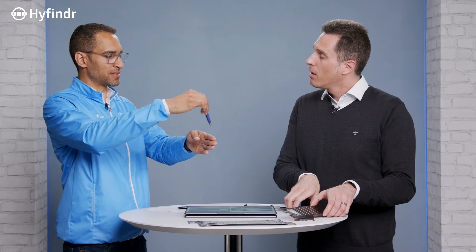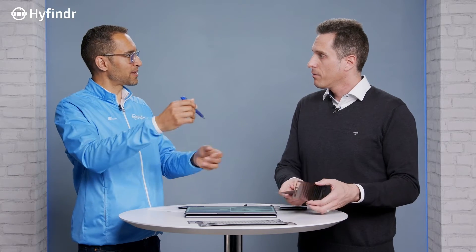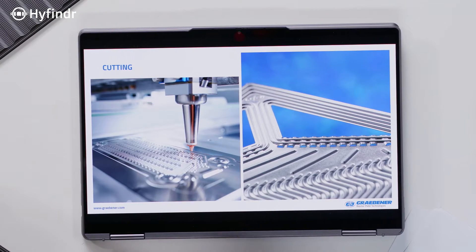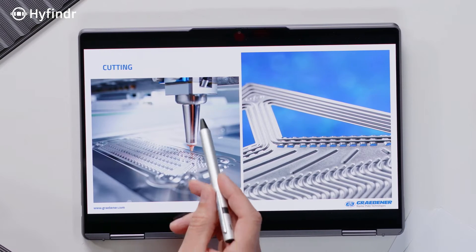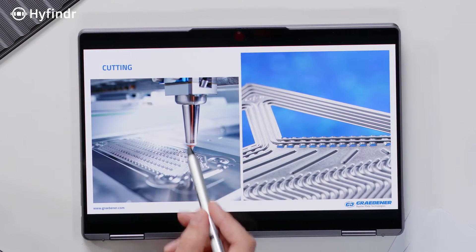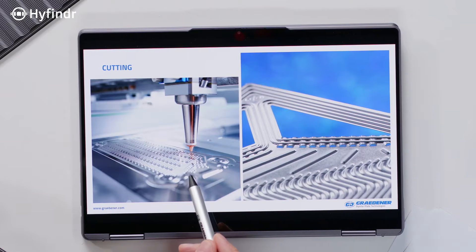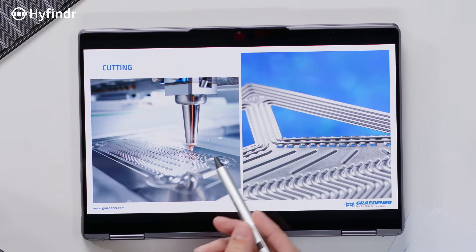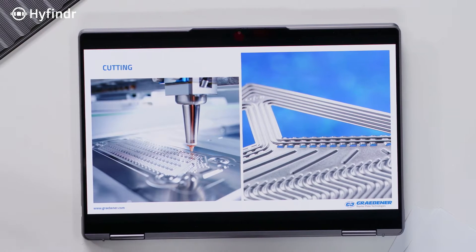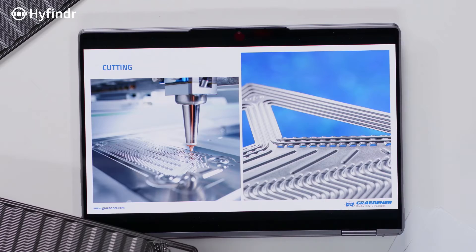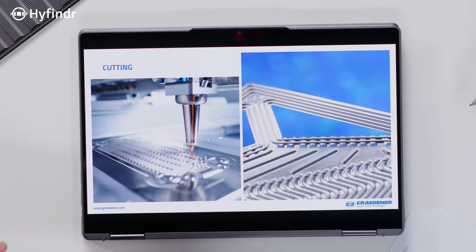When you laser-cut it, does the part just fall off? The small parts — this is a special process. As you can see here, this is a process where we are using nitrogen in the cutting process. The nitrogen is responsible for having a very good edge quality, and it also blows the material away, which is good for the next process.